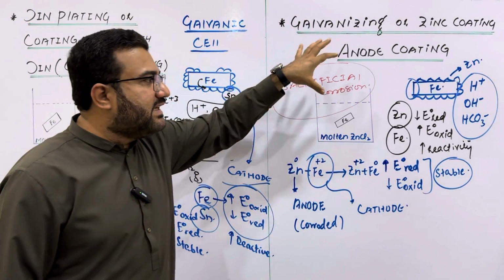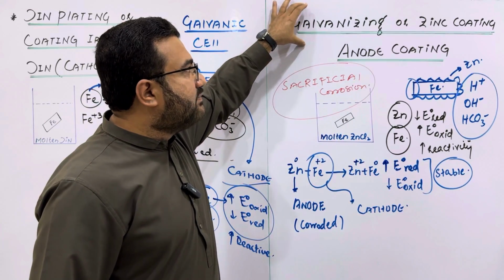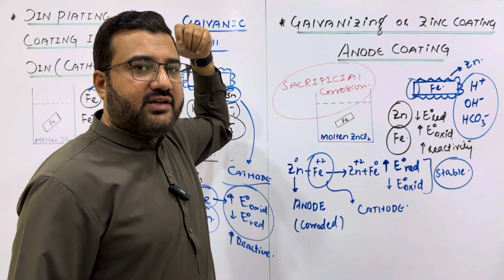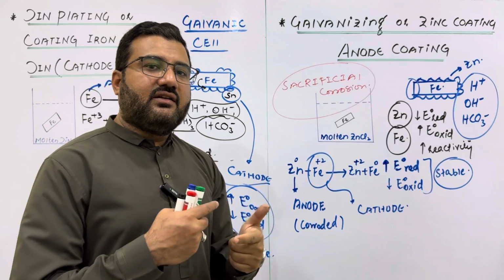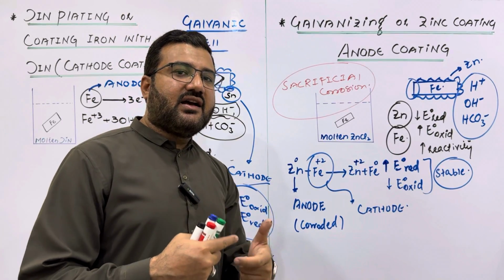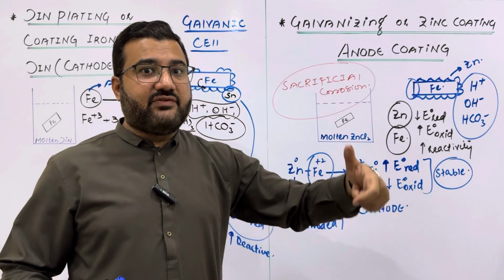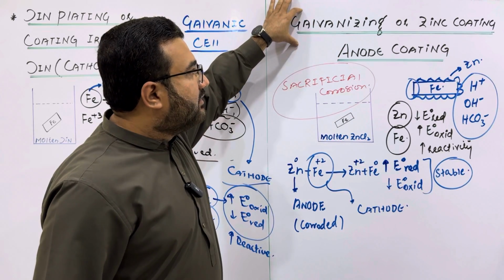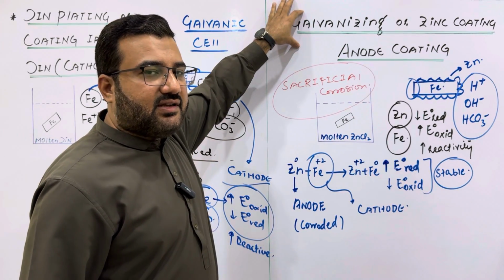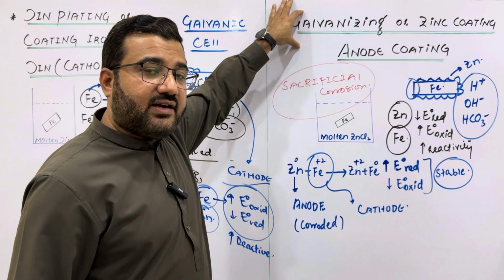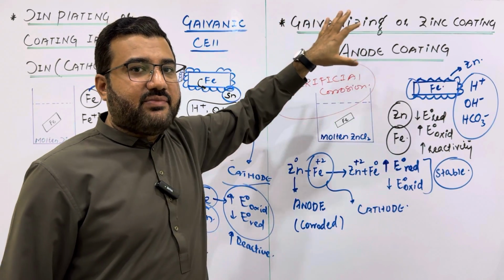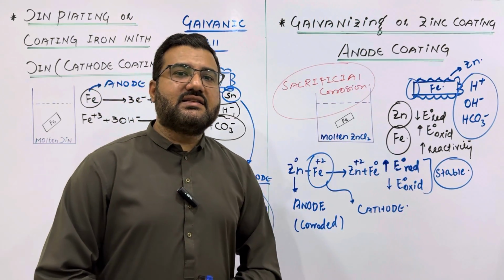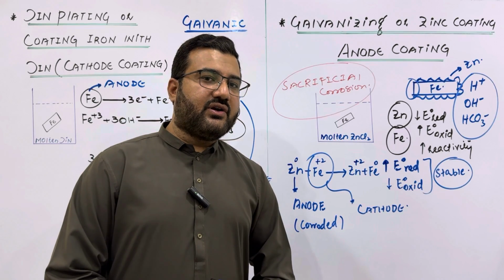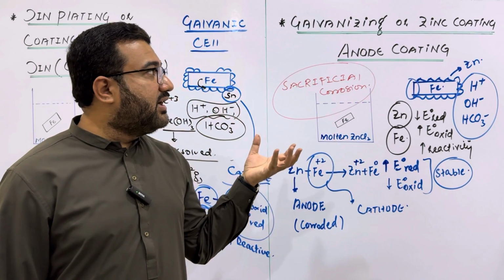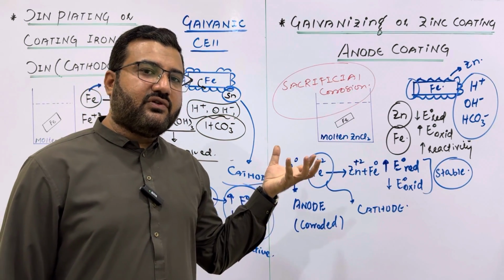Now you can easily judge that this technique is much more beneficial as compared to the tin coating, because if the coating of the tin is damaged, the corrosion of the iron becomes even faster. But if the coating of the zinc gets damaged, iron remains protected. Zinc itself is corroded, and that is a big sacrifice for iron, and it is called sacrificial corrosion. So these were two modern techniques to protect iron from being corroded.